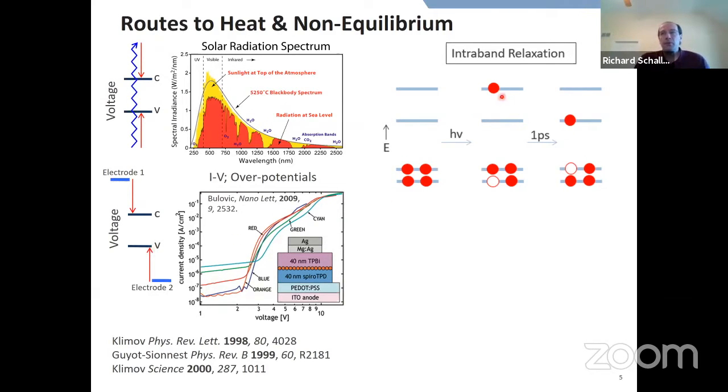One of those is intraband relaxation, which has been looked at for a very long time in nanoparticles, going back to dates prior to these references. There are even arguments that electrons might be able to live up in higher energy states than the conduction band maximum, because there are energy gaps that may be larger than the available phonon energies in the system. And so your electron can't just fall down by emitting 1 phonon to get to the band edge. It may have to emit 5 phonons or something like this. And so those processes involving lots of carriers simultaneously could in principle be inefficient, so you might have long-lived hot carriers.